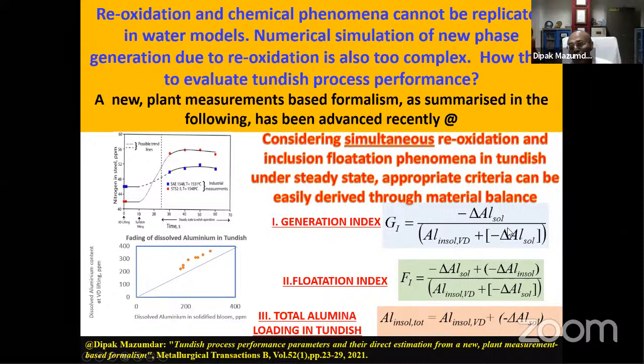The cleanliness of total inclusion loading in the Tundish itself, you can find by measuring this. As I said at the top of the slides, a water model will not be able to capture the reaction part, and when new phases are generated, that will also not be captured adequately, because we require very sophisticated models which can model across length scales, including nucleation, growth and precipitation of new phases and so on. So perhaps by measuring the changes in aluminum content, you could formulate this criteria.